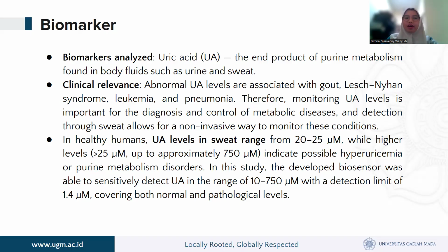In healthy humans, UA levels in sweat range from 20 to 25 micromolar, while higher levels, above 25 micromolar up to approximately 750 micromolar, indicate possible hyperuricemia or purine metabolism disorders. In this study, they developed a paper-based sensor that was able to sensitively detect UA in the range of 10 to 750 micromolar, with a detection limit of 1.4 micromolar, covering both normal and pathological levels.